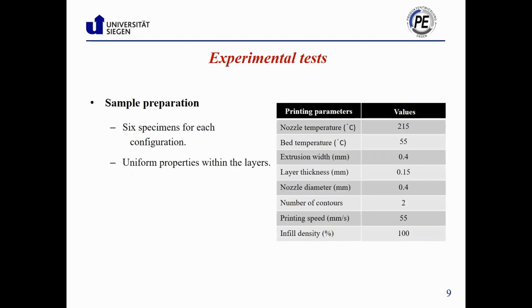Here, printing parameters such as nozzle temperature, printing speed, infill percentage, and layer thickness are summarized in a table. For example, bed temperature was 55 °C, and we used a nozzle with a diameter of 0.4 millimeter in fabrication of the specimen. It should be noted that printing parameters were kept constant in fabrication of all specimens.